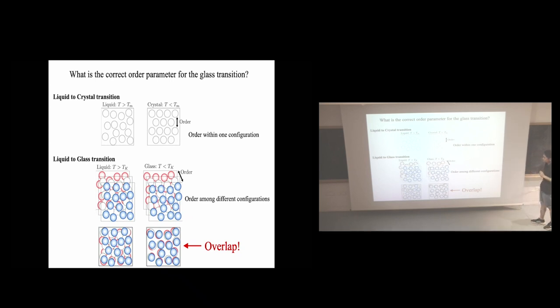one configuration. But in the case of the liquid to glass transition, since liquid and glass are almost the same, well, by just looking with the eye, you cannot detect order from a single configuration. Instead, we have to see many different configurations. And what we see is actually detecting order among different configurations. That is called overlap.